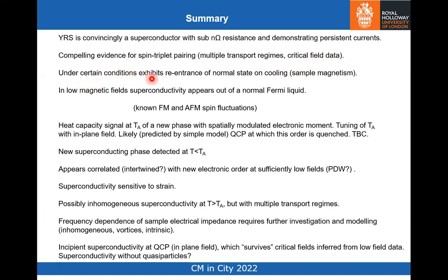Under certain conditions, we see re-entrance of the normal state on cooling. That has to do with sample magnetism, at least in part, because it's anisotropic for the two field directions, and this material is magnetically anisotropic. In low magnetic fields, despite what anybody tells you, the superconductivity appears out of a normal Fermi liquid. We know that we have ferromagnetic and antiferromagnetic spin fluctuations in the system. So my guess is that they're the driver.